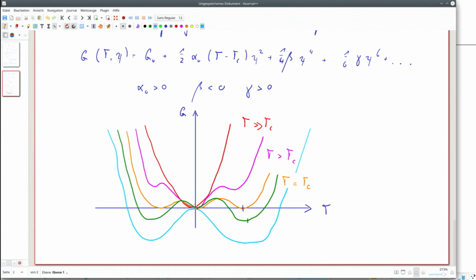So what does it mean? First of all, it means that the equilibrium degree of order, which is 0 here, at the critical temperature jumps to a finite value. This is what we expect for a first order phase transition, an abrupt change in order. Sorry, I always use S here because in my manuscript some time ago I used S here, but that's fine. So the degree of order slightly goes down if you go up here. So this minimum here moves a bit to the left, but then at the critical temperature it jumps here.